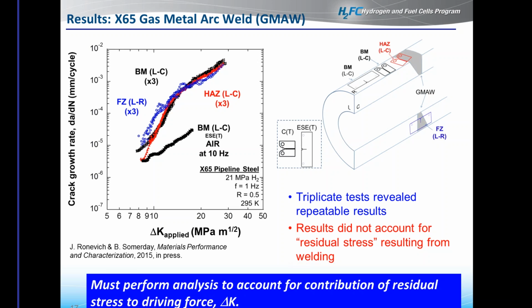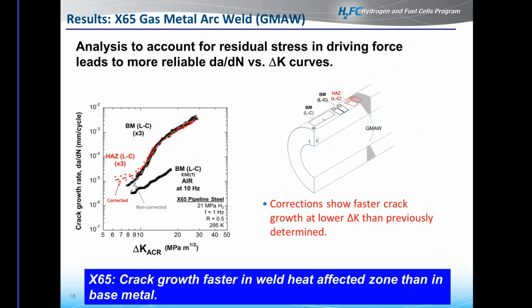So we did some further analysis specifically on the heat affected zone. And what we found was when we removed the effects of residual stress, we got a shift in the curves. And I've identified them as the non-corrected version, which was what we saw on the previous slide, and the corrected version that's shown now on the red dash line. And so really what this da/dN versus delta K curve shows us now is that once you remove the effects of residual stress and you're using a known driving force, you can actually measure the material response more accurately and more reliably.